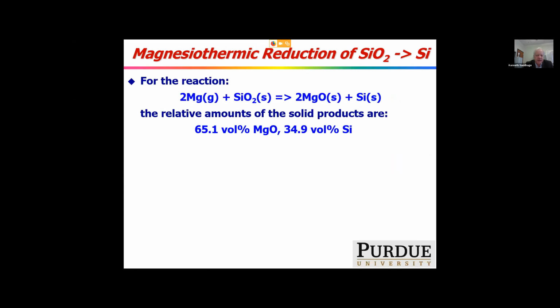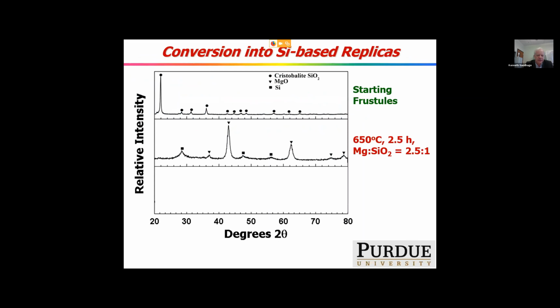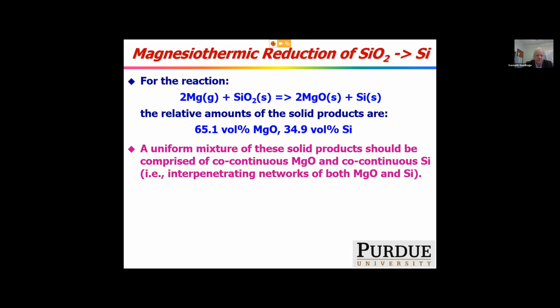In this case, to make silicon, we use a reducing agent, magnesium vapor. So magnesium gas can react with silica to form magnesium oxide and silicon, again a displacement reaction. The oxygen is displaced from silica to magnesia. That gives you a product with about 65% by volume MgO and 35% silicon. By X-ray diffraction, we can do this at quite low temperatures. Magnesium is a very effective reducing agent, and you can see quite broad peaks for MgO and silicon. It turns out that in this case, at these temperatures, we get a co-continuous mixture of MgO and silicon. You can dissolve either phase away and maintain the structure, albeit porous.